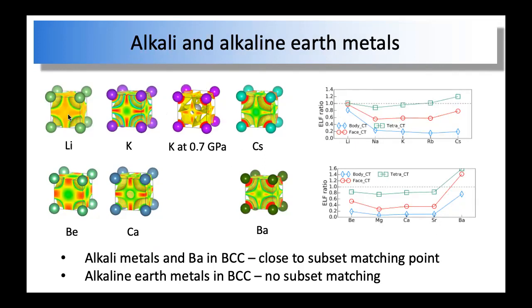However, lithium has complexities, and I will show you. That is why all these points are getting close together. That's because lithium not only has matching, but at the same time it also has repulsive interaction. It also has very large electron localization in the body center. So the lithium case is more complicated than the other cases. And for the other alkali metals, even if they are not at the perfect matching point, they're very close. If you just compress them a little bit, you shift to the matching point.